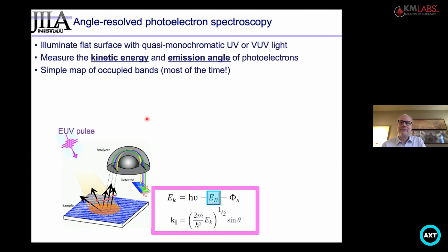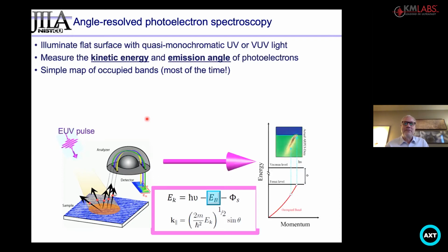And if you look at what happens to the direction of motion of those electrons, it's very much like a Snell's law. If you have an electron going through a flat surface, the component of momentum perpendicular to the surface changes, but the momentum parallel to the surface is constant. And what that allows you to do, by looking at the angle of emission of those electrons, is get a map of the band structure of a material, or something that's very, very close to the band structure of a material. And here's a simple example of angle resolved photoemission done with a laser, where you see band structure, in other words, K vector versus energy, all the way up to the Fermi level of the surface.